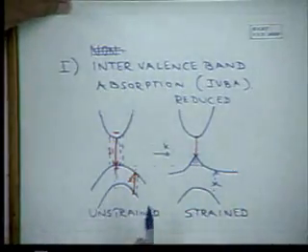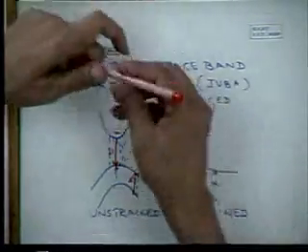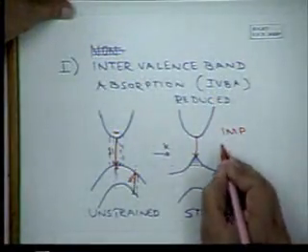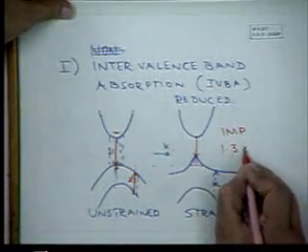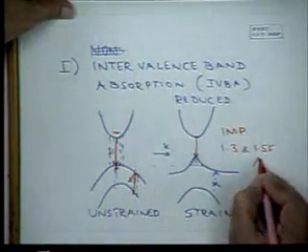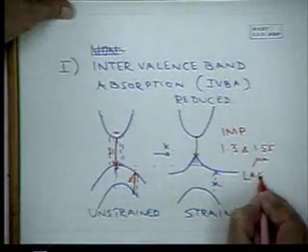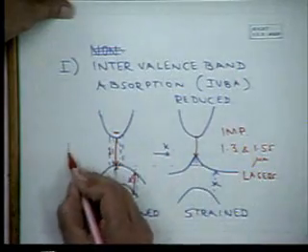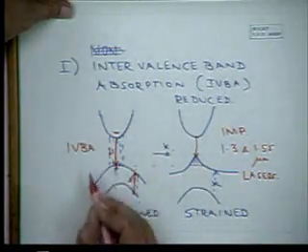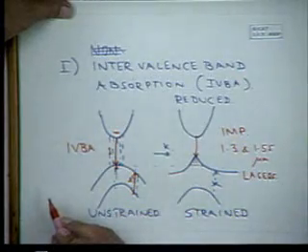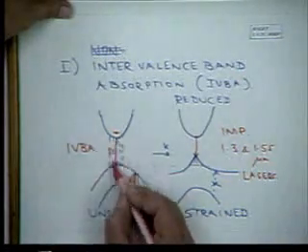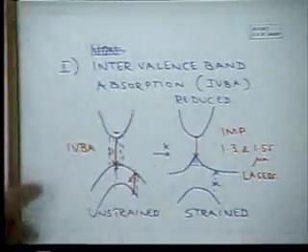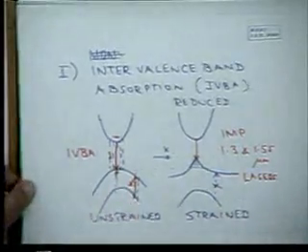So this is quite important for 1.3 and 1.55 micron lasers. If IVBA occurs, then the threshold current increases, and it reduces the quantum efficiency above threshold due to this inter-subband absorption.